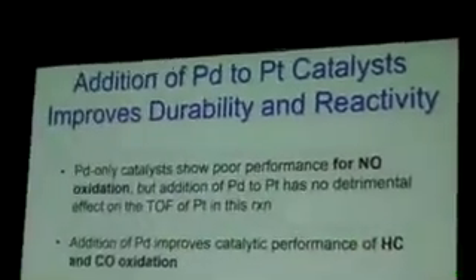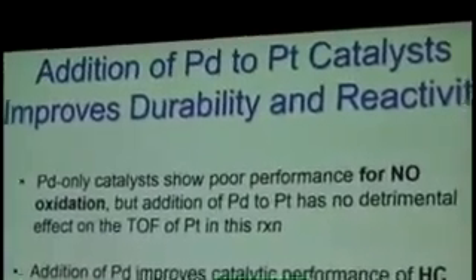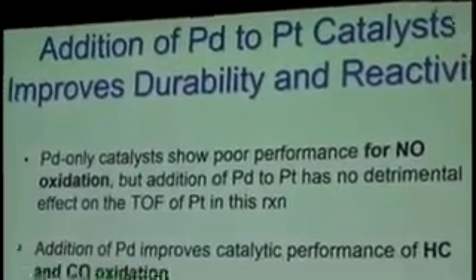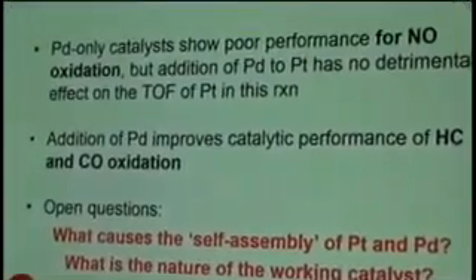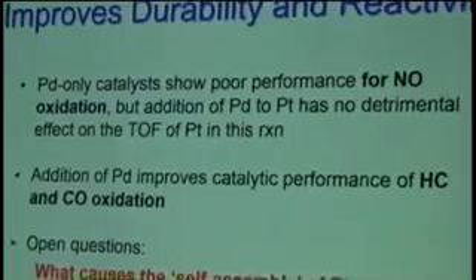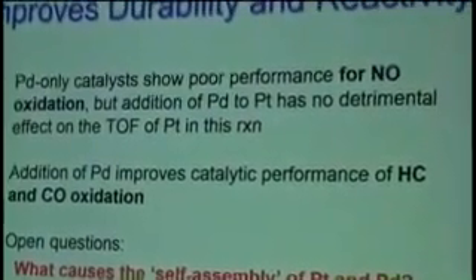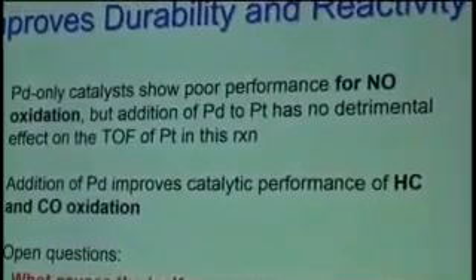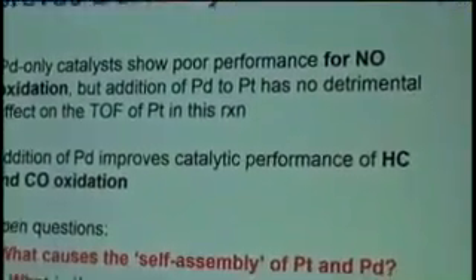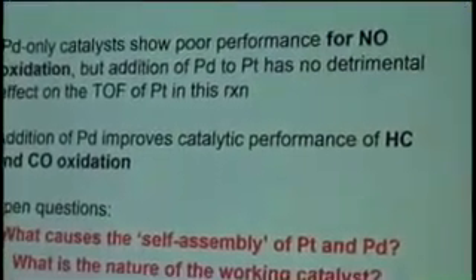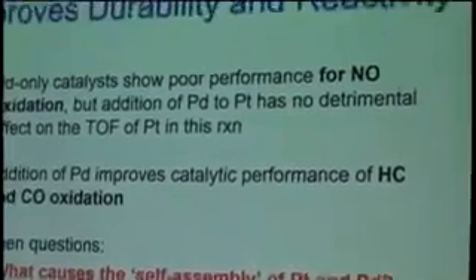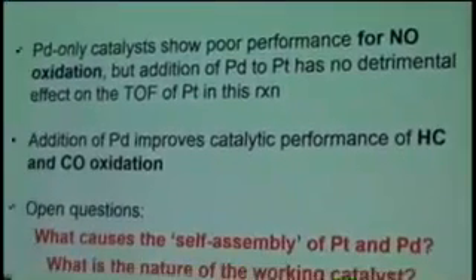So in summary, addition of palladium improves both the durability and the reactivity. So it's a good thing, and we want to understand how it works and how to make it even better. So, first important fact, by itself, palladium is not very good for these reactions, for these oxidations. But it's there because it plays an important role. And it will improve the performance in some of the carbon oxidation, but not NO. So we want to know how exactly does that happen in actual reactions.